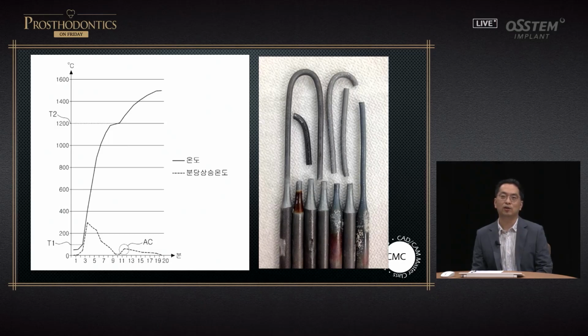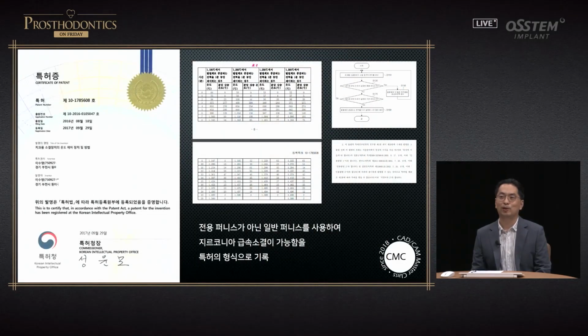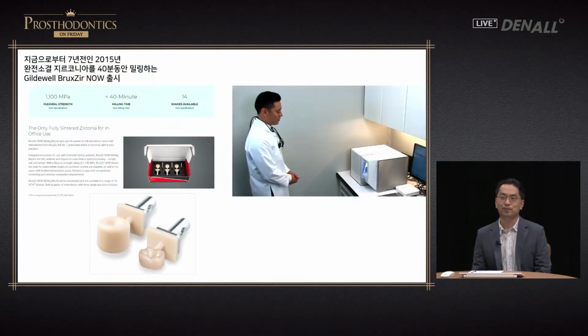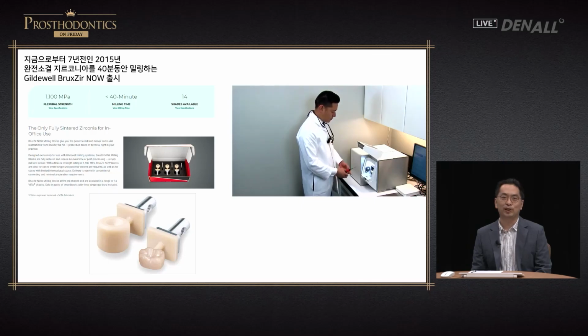Rather than providing bigger electricity to generate the heat, I realized that if I reduce the hot wire temperature to 1,200 degrees before applying electricity, a faster temperature increase per minute could be achieved. Using this method, I was able to reach 1,500 degrees within 20 minutes, and I was able to get a patent. This shows that rapid sintering is possible using just an average furnace.